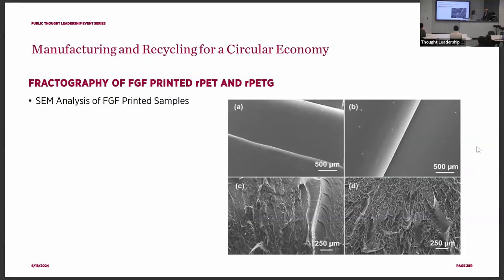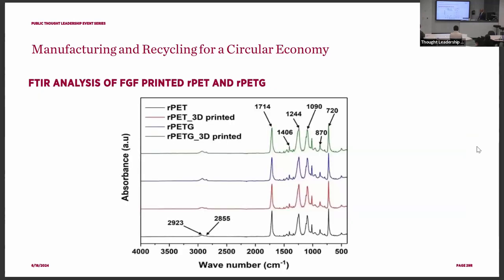After that, we also do the analysis. SEM analysis just looks into all the samples. Are they good? According to this SEM, on the left-hand side, A and C are about PET, and on the right-hand side, B and D are for the PETG. When you look at the result, the material is pretty good. That means recycled material doesn't mean the material is bad. They are good, right? And we did an FTIR analysis to look at the structure change. Looking at this comparison, RPET, RPET 3D printed, RPETG, RPETG 3D printed, you can see all these materials have very similar performance. There's no significant change made by 3D printing, so we are happy with that.